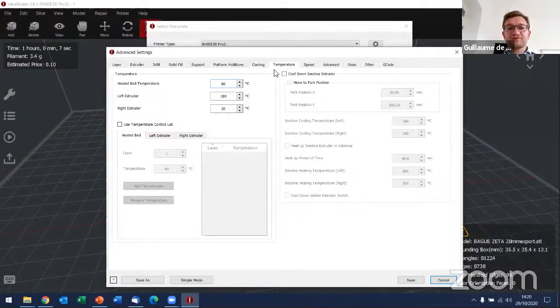Temperature is, of course, important. The extrusion temperature is really critical. One of the interesting things is with our materials, we usually don't need very high extrusion temperature. We're usually below 200 degrees C, sometimes 220, never more, which means it's compatible with most printers. All of the printers can go up to 220. You don't really need a heated chamber. You don't actually need a heated plate. So that makes it really compatible with most printers on the market.